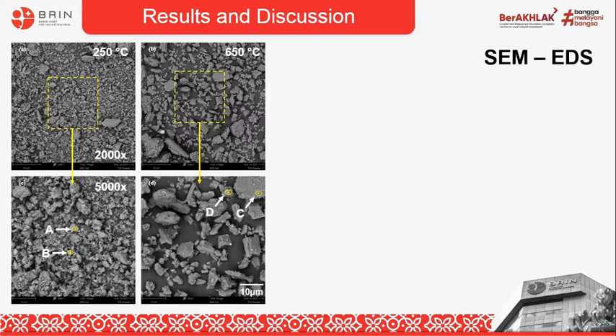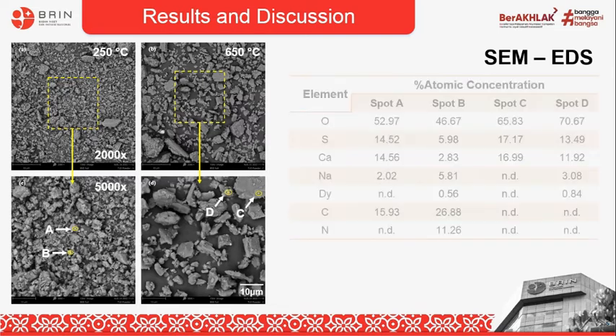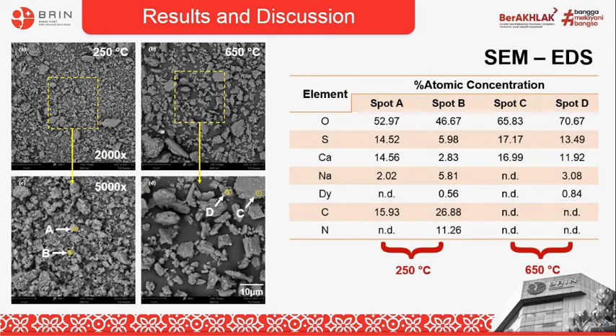Smaller particles were found at lower heating temperature, presumably due to the existence of an amorphous compound containing carbon that may come from an organic substance, that is ethanol, as measured using an EDS detector. The calcined powder exhibited a prismatic crystal shape. The EDS measurement was used to analyze the elemental composition of a certain area in the BSD image. The atomic concentration of several spots marked by A till D was summarized in this table.